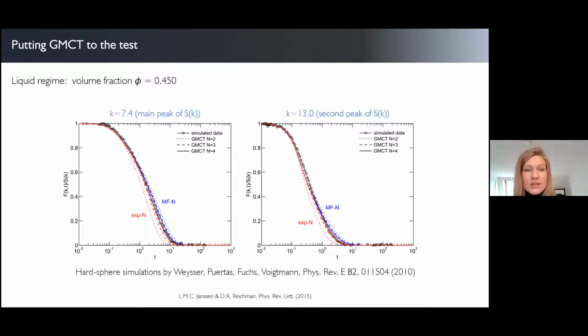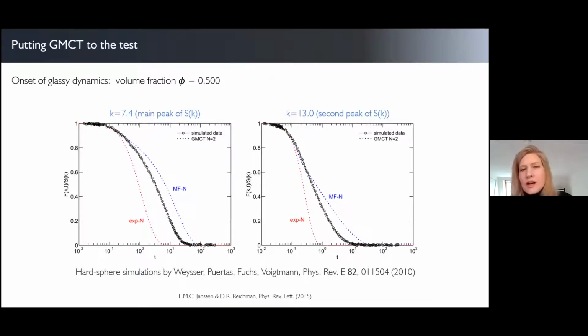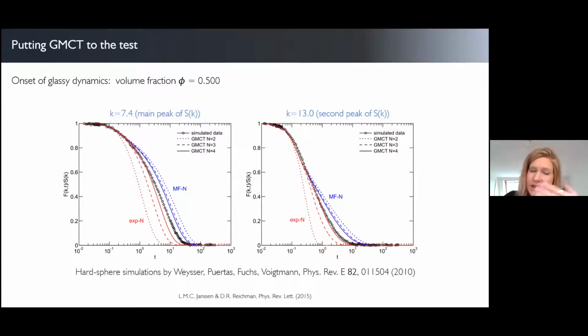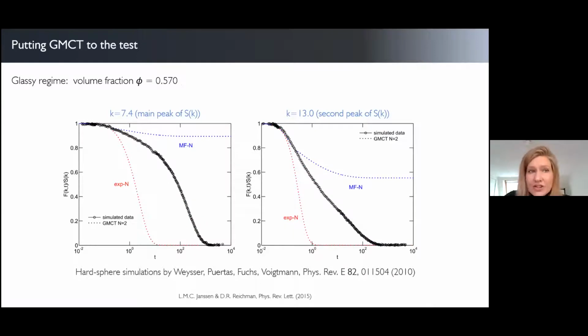So that's encouraging. Then going to slightly higher volume fractions of 50%, this is where we start to see the onset of glassy dynamics. And here you can see that mode coupling theory in its standard form already tends to overestimate the dynamics quite a bit, as in it predicts too slow dynamics. But going to higher order generalized mode coupling theory, we again see that we systematically approach the result of the simulation. And finally, the highest volume fraction I could calculate at the time, at 57%.